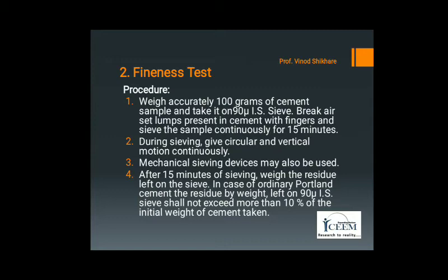After 15 minutes of sieving, weigh the residue left on the sieve. In case of OPC, the residue by weight left on the 90 micron IS sieve shall not exceed 10% of the initial weight of cement taken. If the percentage of residue is greater than 10%, the cement is not fine as per IS standards.